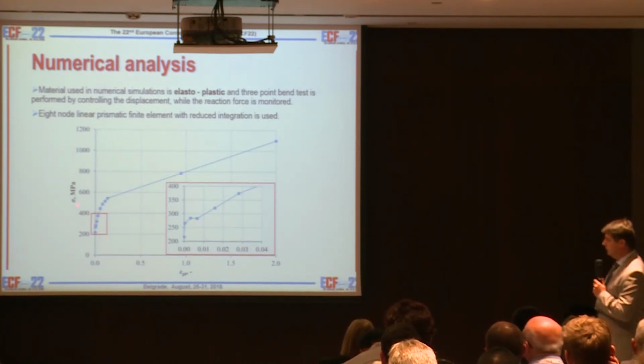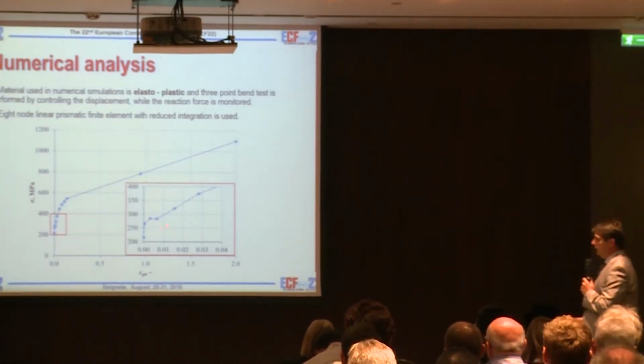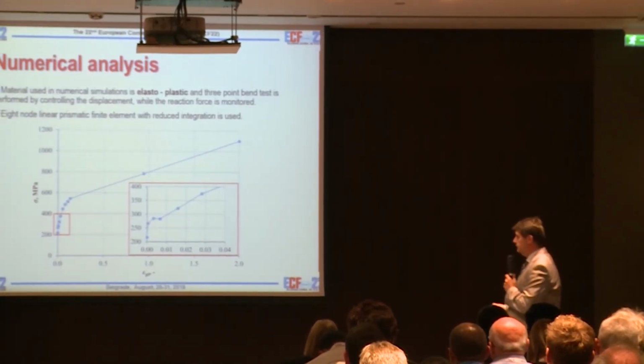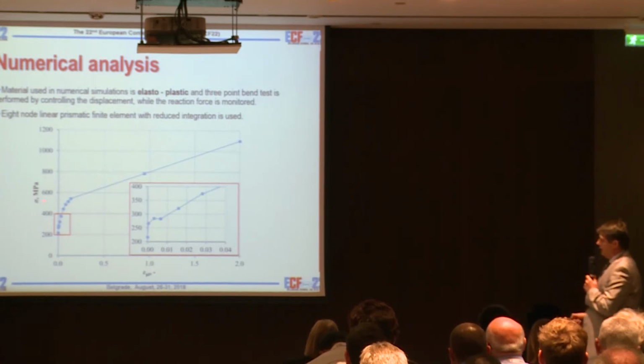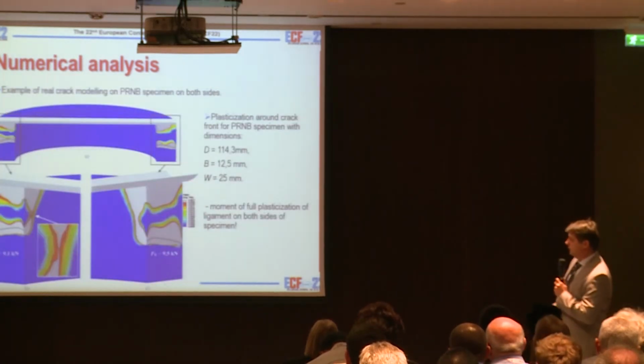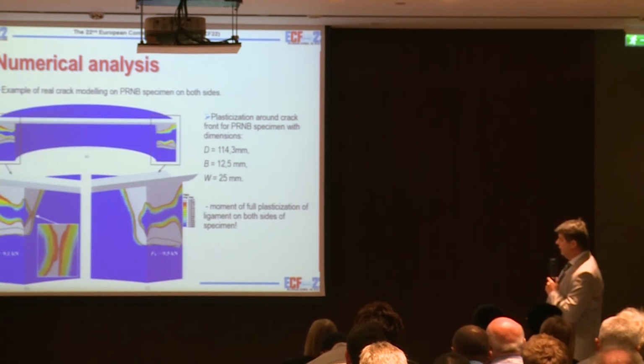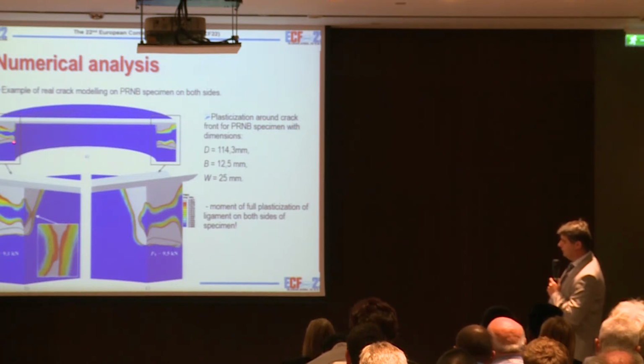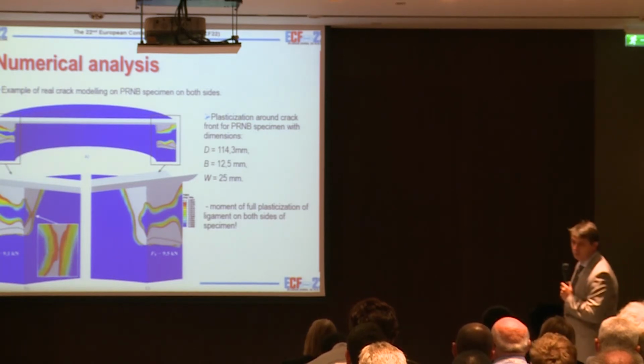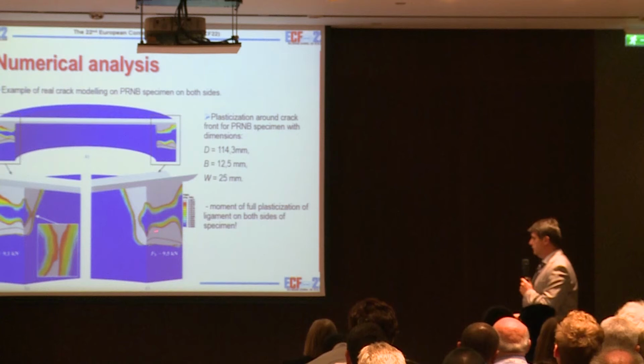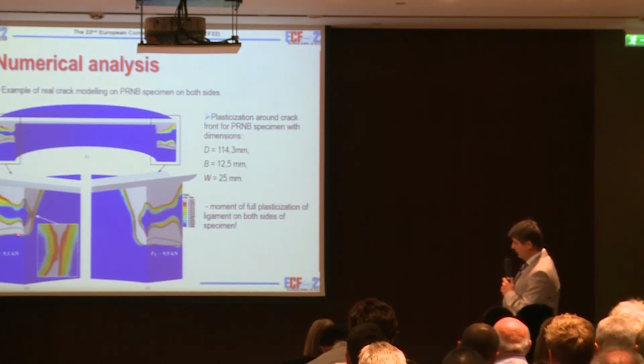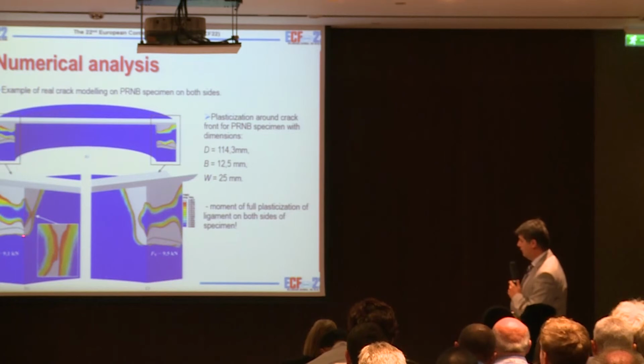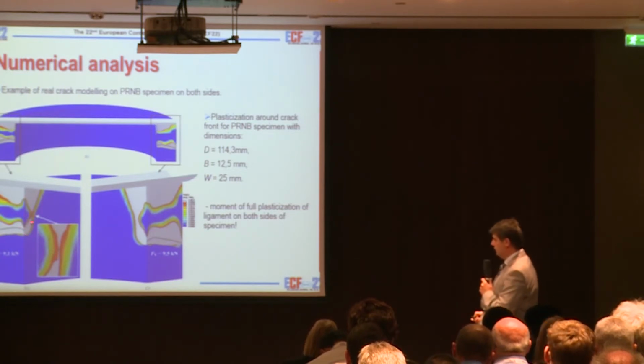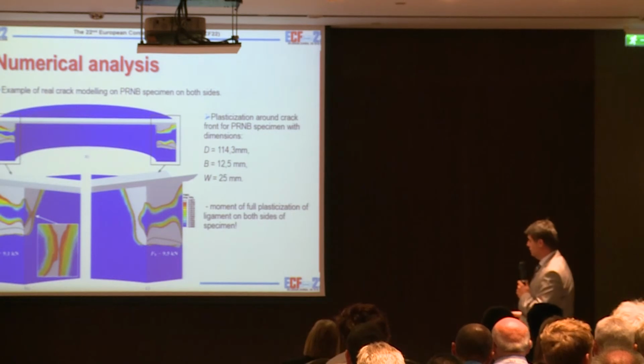Also, we use the model. It is a stress-strain diagram of the material which we use. This is the real test data, and we have the elastic and the elastic-plastic part which we use in the analysis. So you can see here the fatigue crack front, and the model was made considering the front on the left side and here on the right side. And here we use half of the model in this case because it was not symmetric. And you can see also that we determine the limit load. So then we have the plasticity which comes from the crack tip to the end of this section.